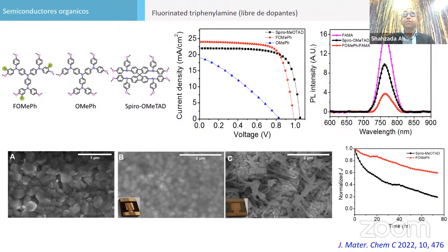Then, recently we have been working on a fluorinated HTM, because fluorine is Teflon, which you use in your kitchen utensils. It repels water, it repels oil. So similarly, we use a fluorinated organic molecular HTM. They also work very well to boost the stability of this material. This is the PL quenching. They show this fluorinated HTM quenches the perovskite very well.